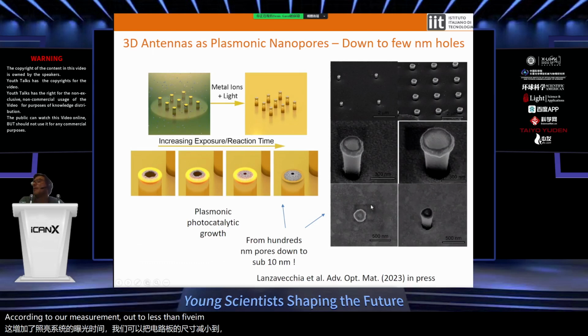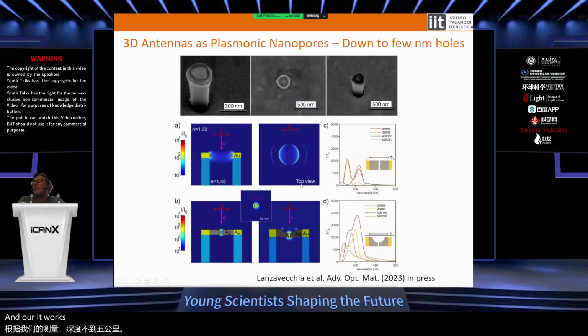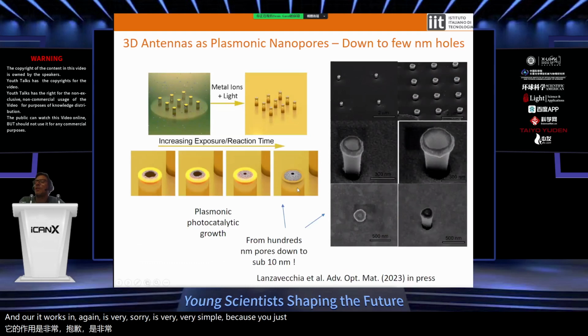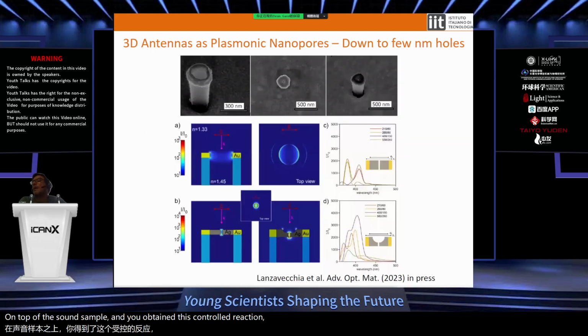And how it works is very simple, because you just need to put your system under a microscope to illuminate everything with light. You drop your metallic salt on top of the sample, and you obtain this controlled reaction. The interesting aspect is that if you look at the electromagnetic field, so consequently at the plasmonic properties, you start from this metallic ring where you have the field confinement inside the ring, but if you then reduce the size of the ring with this photochemical reaction, you can have a much better confinement of the field down to few nanometer as you want for a single molecule detection with a nanopore.